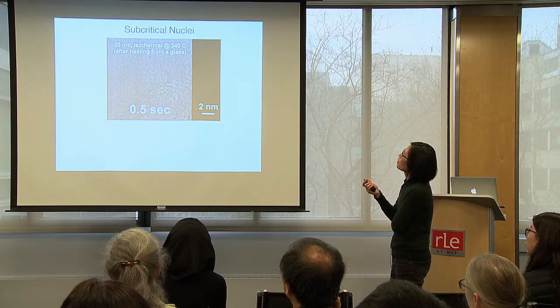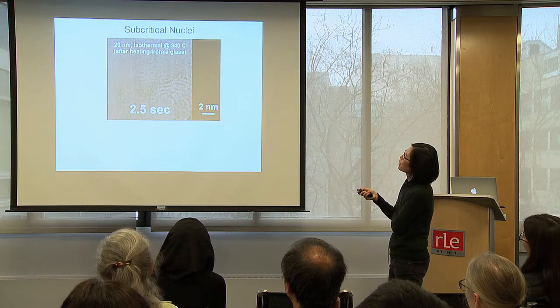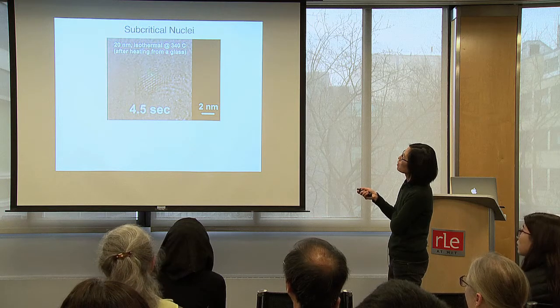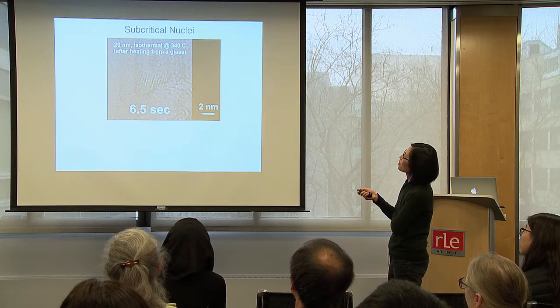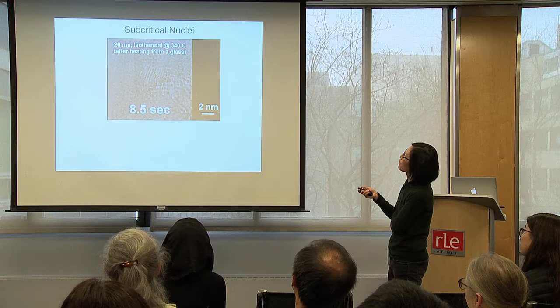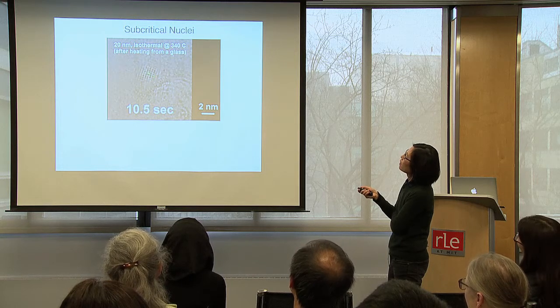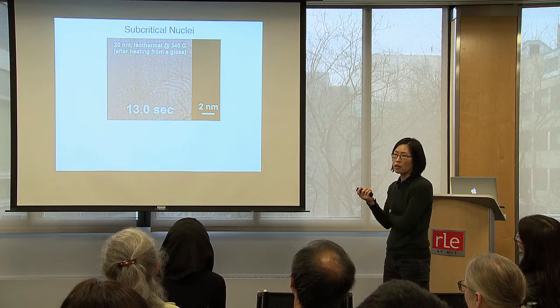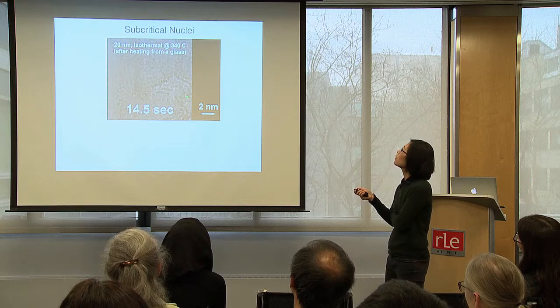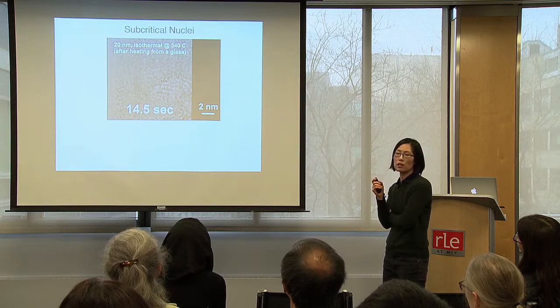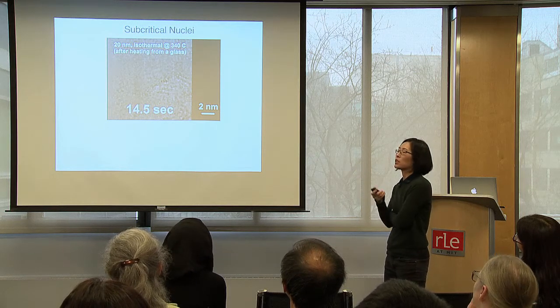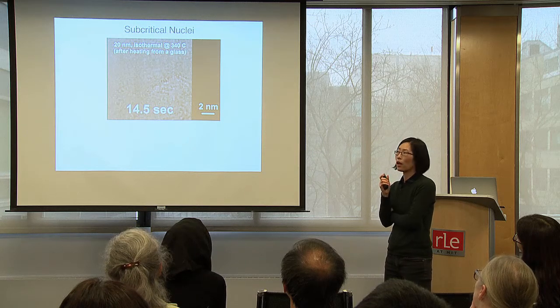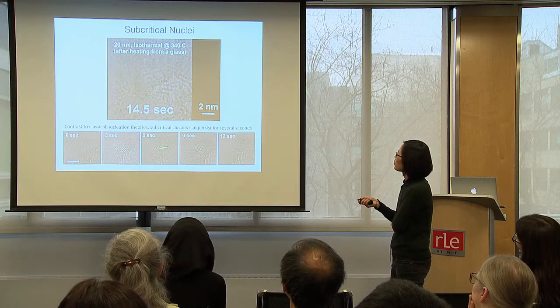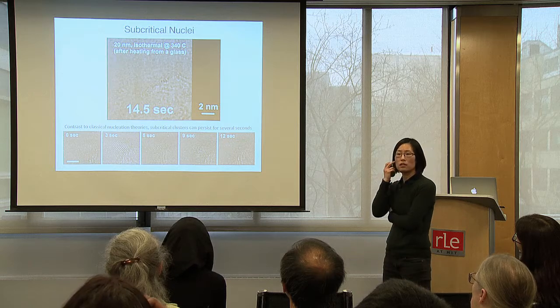Here's a proof of the subcritical nuclei being very stable. Here's a cluster of about 1 to 1.5 nanometers that pops up, and then it's rotating around. And it's quite stable for 6 to 7 seconds, even though we're sitting at 340 degrees Celsius. And then once it disappears, we never saw it again. Okay? So you see that it persists about 6 seconds.